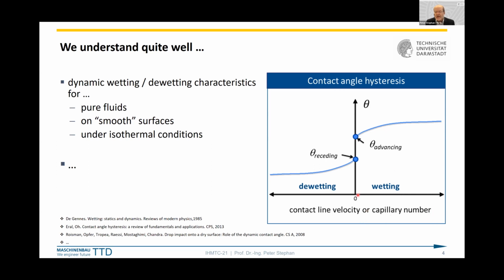So here we have a wetting situation, and here we have a de-wetting situation. In a wetting situation, typically with increasing wetting velocity, the contact angle is increasing, and with increasing de-wetting velocity, the contact angle is reduced. And then we can have a hysteresis, depending also on surface roughness effects and so on.